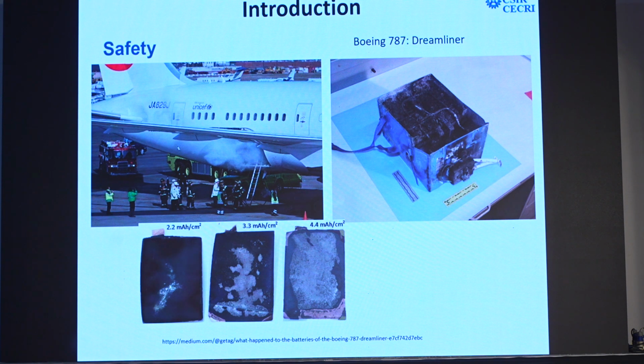Thermal runaway is when the lithium-ion battery, through parasitic reactions inside, releases heat, which will further lead to explosion. The reason behind this explosion is mainly oxygen evolution. And this oxygen evolution mainly happens when you have an unstable positive electrode, or a negative electrode which is graphite, on which your lithium will go and plate, and this plated lithium is highly inflammable. It will catch fire very easily. So that's why, due to the high cost and the safety concerns of lithium-ion batteries, people were thinking of an alternative.